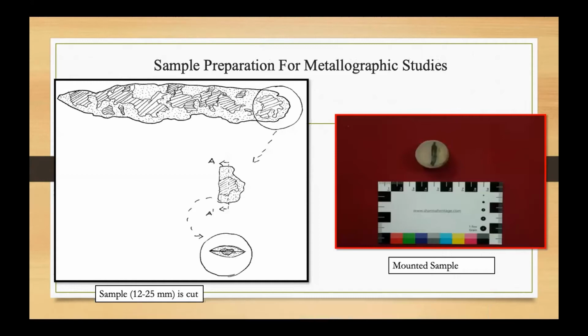So the next slide shows how we prepare the samples for metallographic study. Here I have given you something like a knife, and you can see the shaded regions are the region which is intact, and the dotted regions are the rusted regions. So you have to understand from where you need to take your sample, because you want your non-rusted region. Because if you get a rusted region, first of all, it's very difficult to prepare your sample, and then you might not get any image out of it.